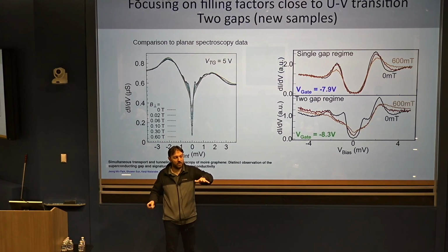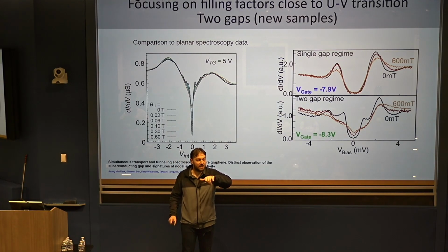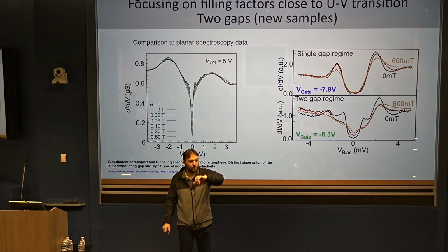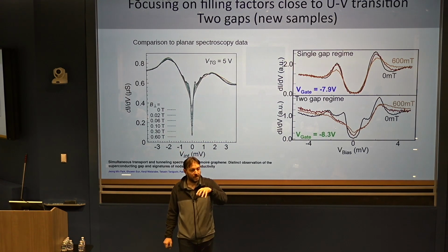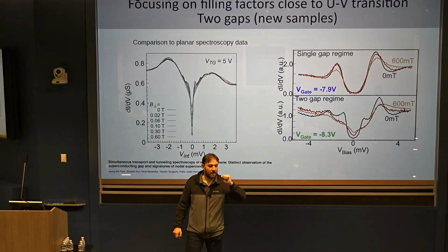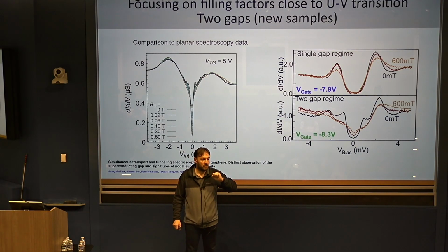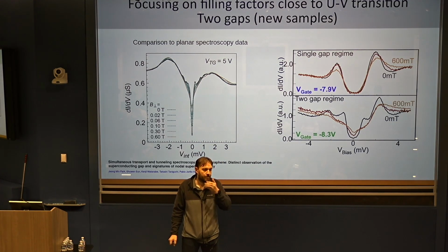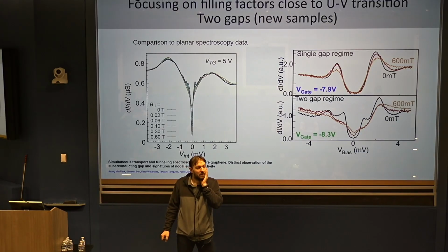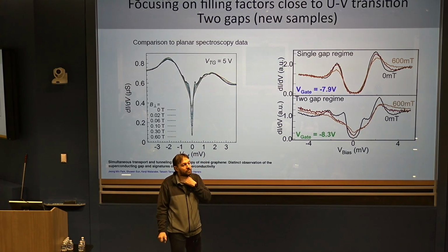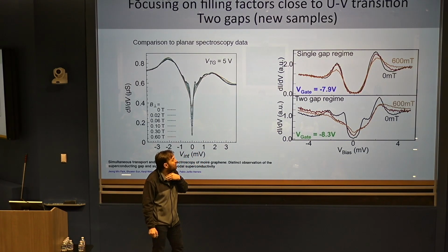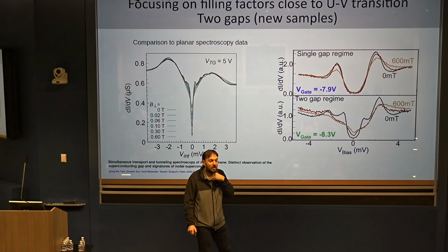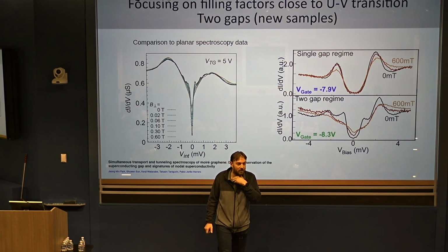The way you do this is you measure the distances of the Moiré pattern in different directions, which are slightly different. And actually, Abhay worked out how to convert that into the heterostrain matrix. Can you purposely apply uniform strain and maybe see if you can reorient? We haven't tried that, mostly because it's difficult.